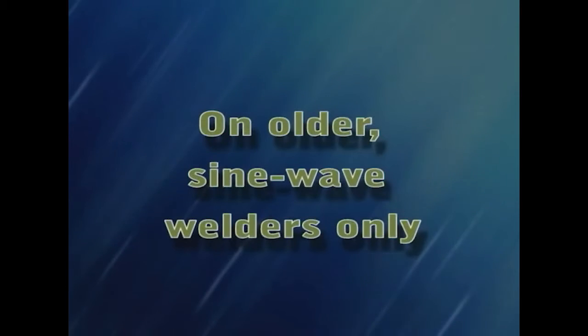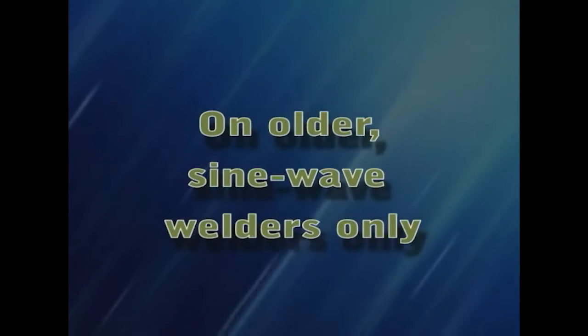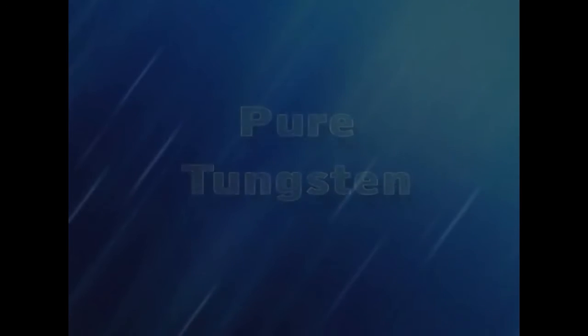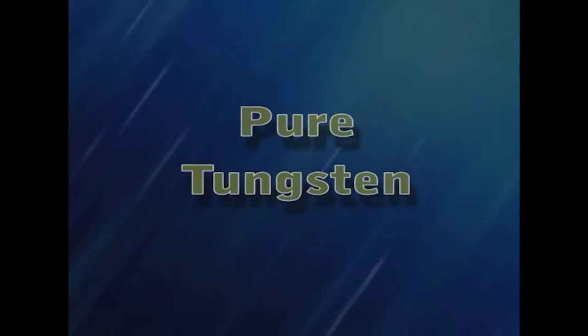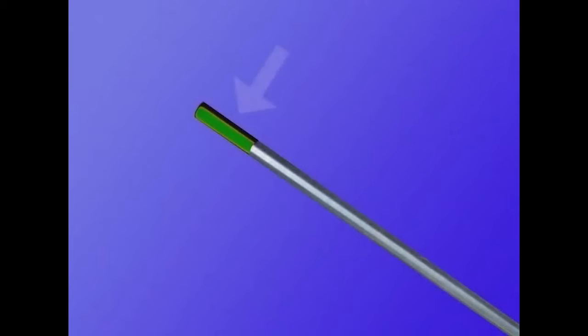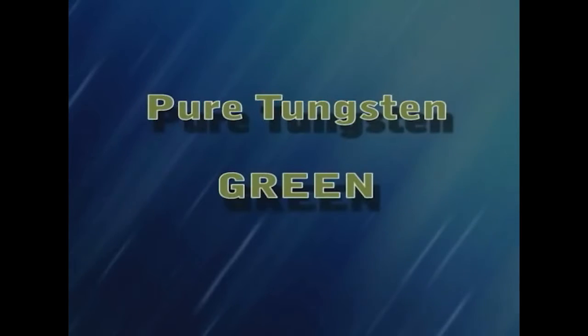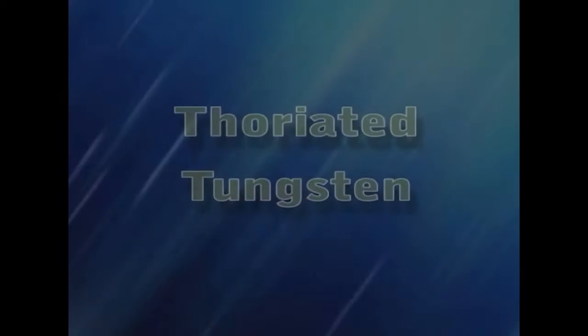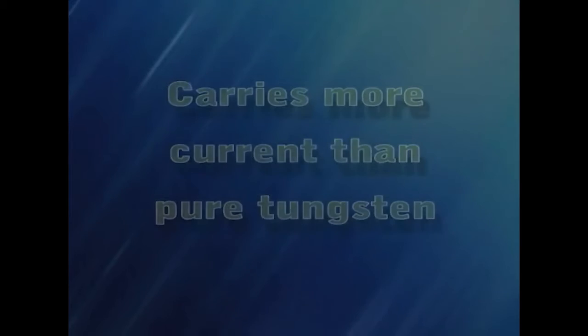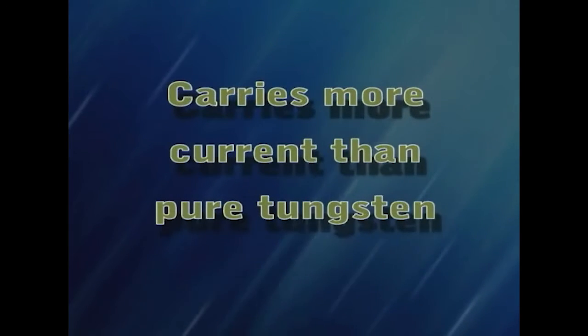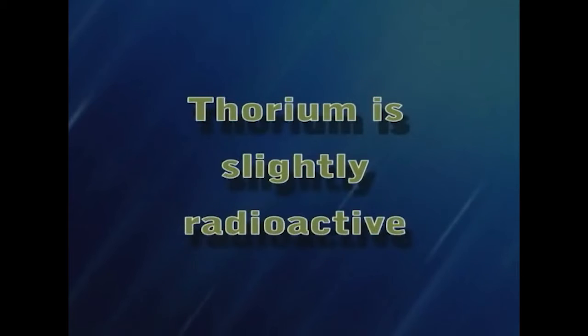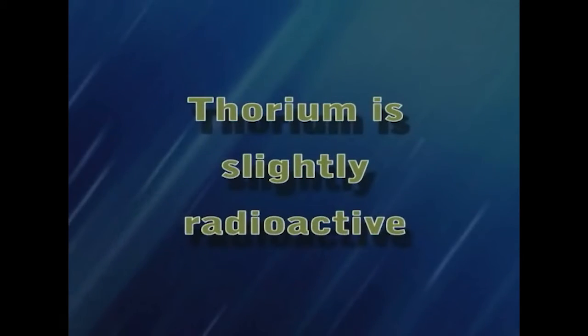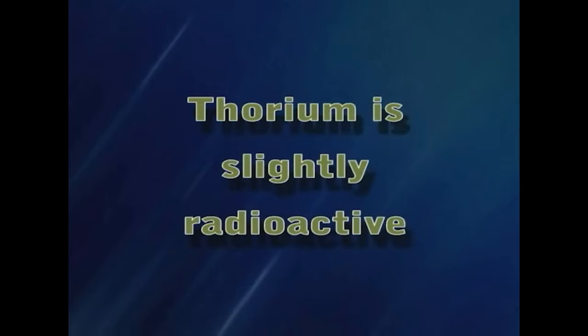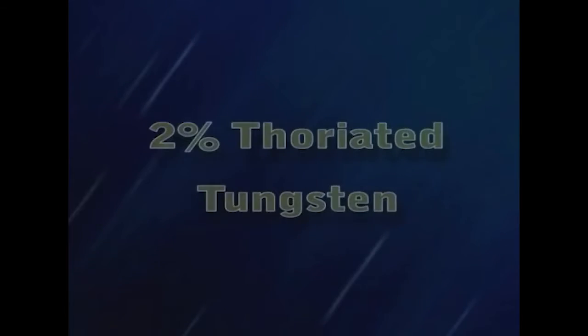For the old sine wave welders, which have been pretty much superseded by square wave and advanced square wave inverter machines, pure tungsten was often used to weld aluminum in the alternating current mode. All tungsten electrodes are color-coded on one end to indicate the type, and pure tungsten electrodes are color-coded green. Thorium has been used for years to improve the arc performance characteristics of tungsten electrode for direct current welding. Although thoriated electrodes are still used, concerns are mounting about the health and environmental risks of thorium since it is a radioactive material. 2% thoriated electrodes, the most popular type, are color-coded red.